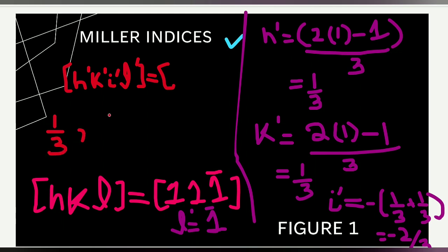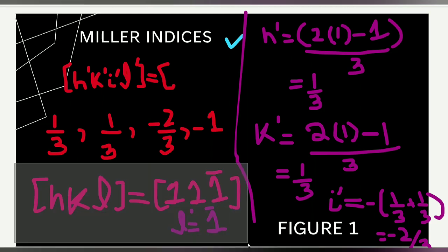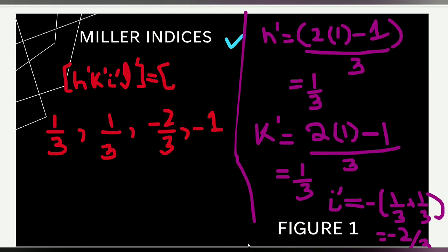This is 1 over 3 for A1, 1 over 3 for A2, minus 2 by 3 for A3, and then minus 1 for the Z direction. We have to remove fractions, and that can be done by multiplying all these indices by a suitable digit, and that suitable digit is obtained by taking the LCM. We can see here that we have 3 in the denominators, all of them are 3, so the LCM of 3, 3, and 3 is again 3, so multiplying all these indices by 3,